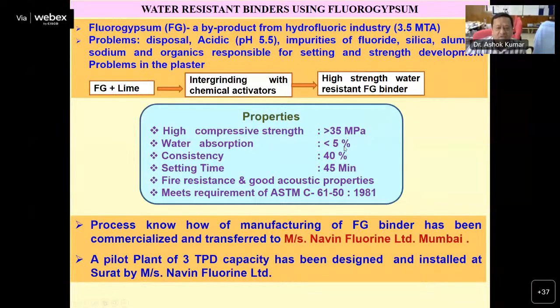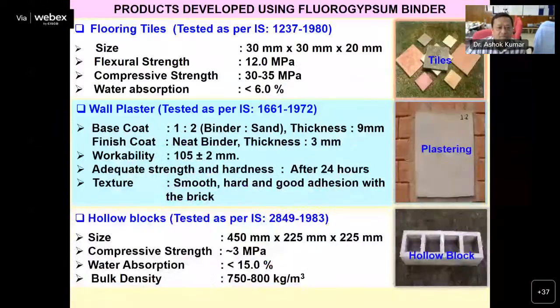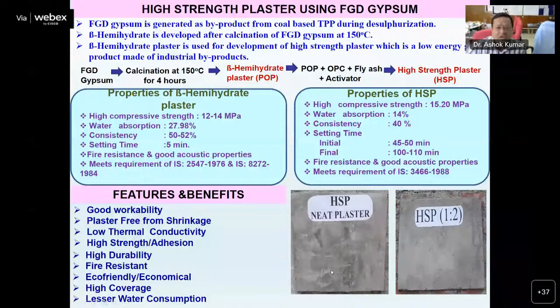This can be used for exterior as well as interior purposes, and this technology was transferred to Messrs. Navin Fluorine Limited in 2015. A pilot plant of 3 ton capacity was also installed at Surat by Navin Fluorine, and they are developing this binder at a large scale. This fluorogypsum binder is also used for development of flooring tiles, wall plastering as well as hollow blocks as per BIS standard methods.